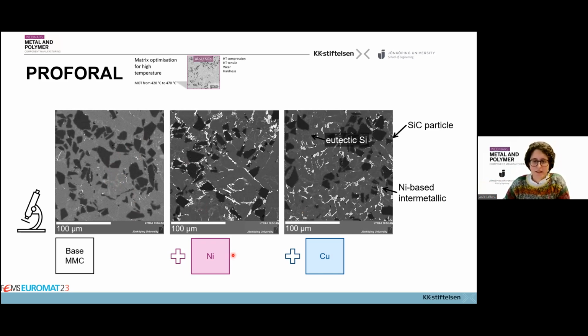When adding nickel, we promote precipitation of nickel-based phases, and those appear white or very bright here in the center picture. So these here are the nickel-based phases. And you see that there is still eutectic silicon here in the background, but a little bit less, with less contrast, let's say, compared to the aluminum matrix. Adding a little bit of copper did not lead to significant change in the microstructure compared to only nickel. We saw that copper was retained in the nickel-based phases and partially also in the aluminum matrix. So we didn't generate additional phases, but we strengthened the matrix and the nickel phases.